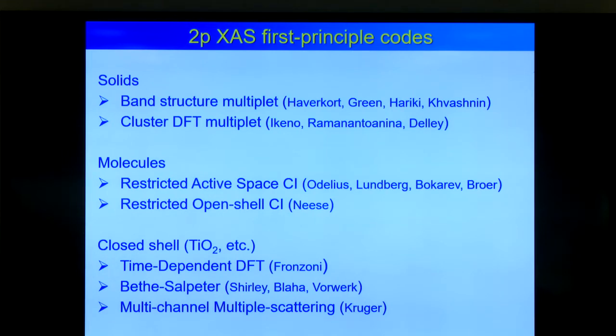Then you have that result, then you take out a cluster in real space from that solid, project your reciprocal space result to the real space by Wannier projection methods, and then in the real space cluster do your multiplet calculation like before. So now instead of parameterized calculations, which I do, you have a first principle route to automatically get all the calculations. A few exceptions, you have to do some tuning, but in principle you have the calculation. So this is in reciprocal space.